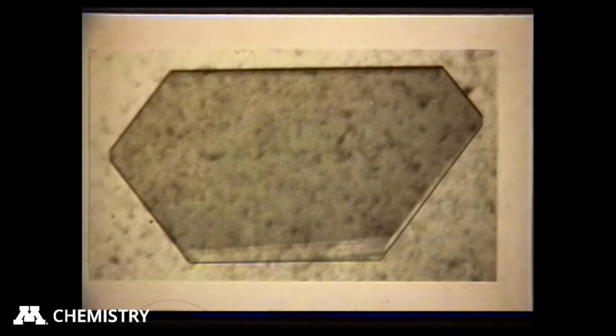All right, now this crystal, this one's about 6 millimeters across. And this would not be a good crystal for crystallography because, first of all, it's too big. But it's too anisotropic. It's very, very thin. But it's a very high quality crystal. The edges are sharp. It's completely transparent. There are no defects in it. But for crystallography, you want a crystal that's nearly equidimensional, because X-rays are absorbed by crystals. And if you have one dimension that's enormous, it'll absorb a lot of the intensity in that direction. And then the relative intensities of your diffraction spots will be all mixed up, and you have to make corrections for it.